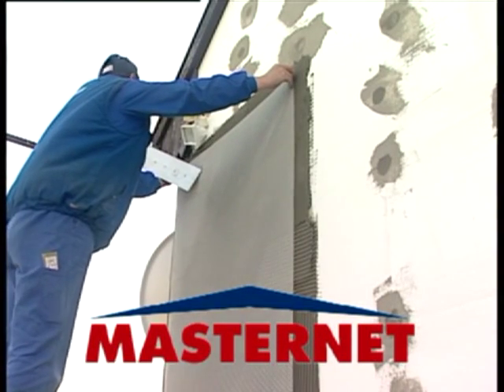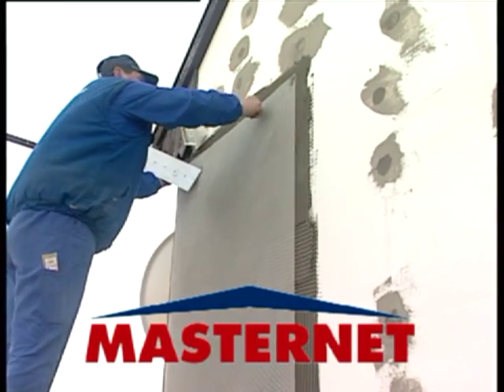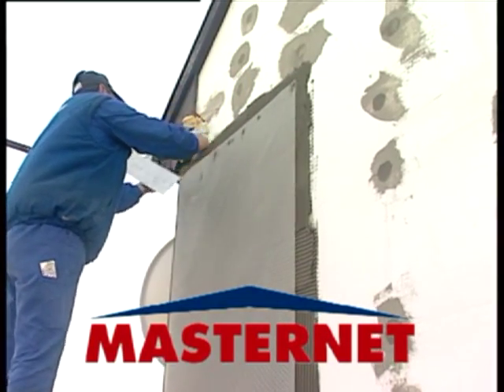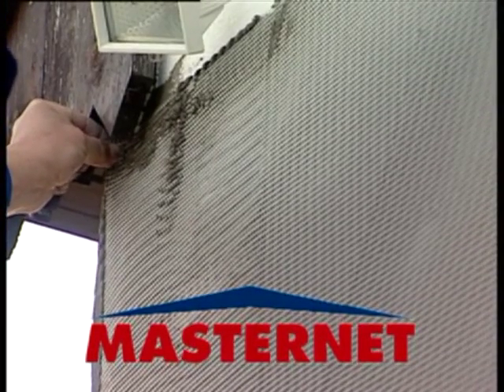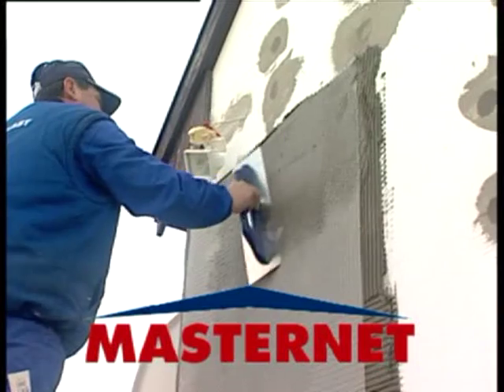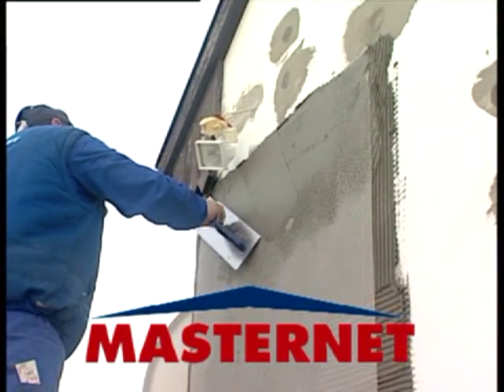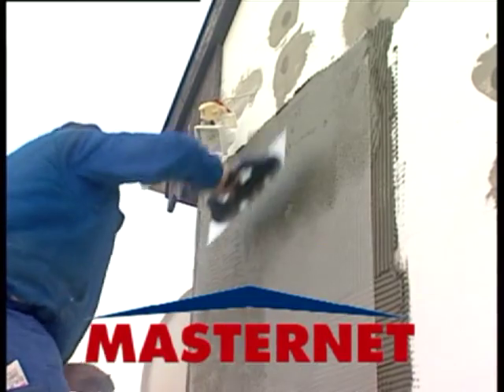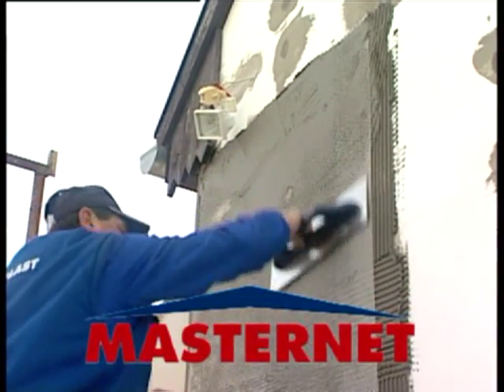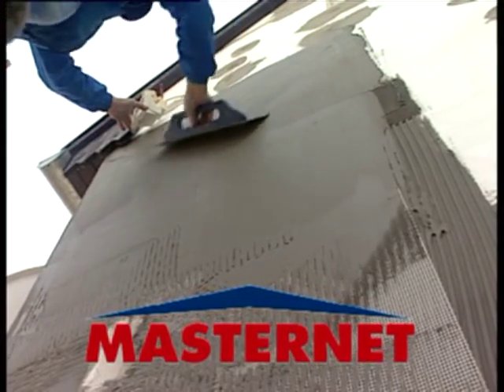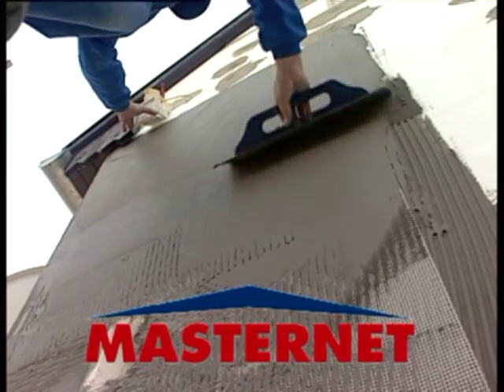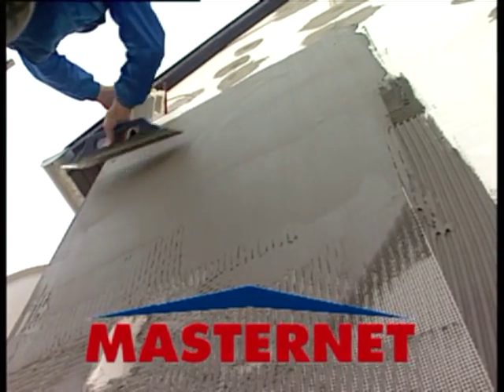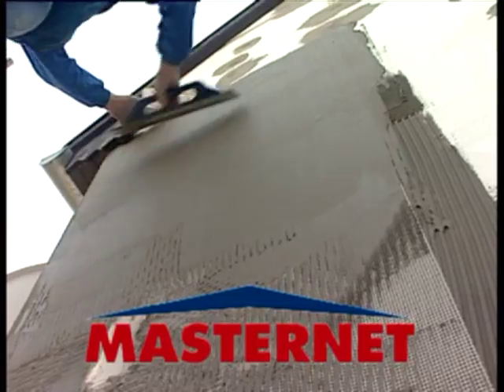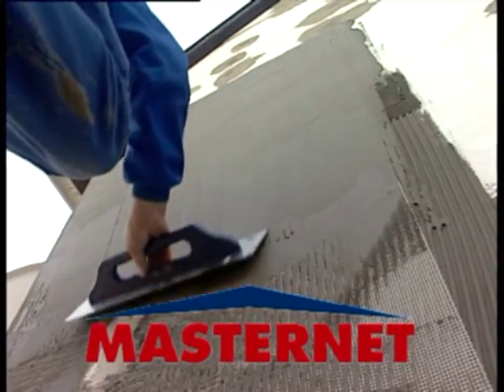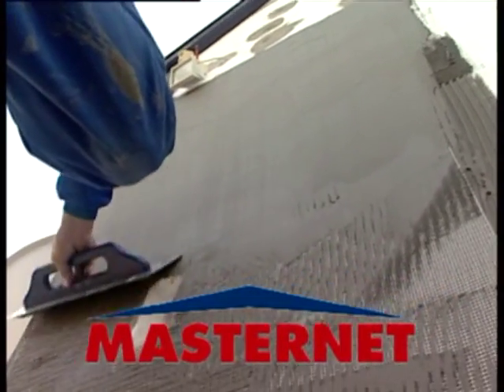The right method of installation is to push the fiberglass mesh into the adhesive layer created by the notch trowel and to gloss the adhesive passing through the mesh. Approximately 3 kg of adhesive is required per square meter for the creation of a 3 mm thick trowel layer. Generally speaking, it is not recommended doing the troweling in warm or windy weather conditions, as even a smaller airflow or sunshine may speed up the setting of the material.